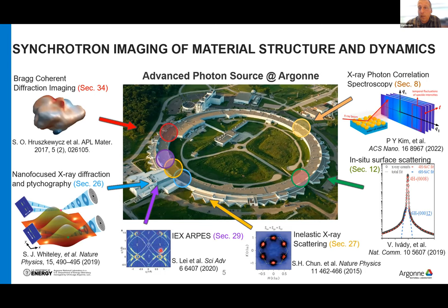But you can also tune the energy to look at excitations. So these fundamental electronic excitations, by using intermediate energy X-ray scattering, also fundamental dynamics of the system, the phonon dispersion, using inelastic scattering as well, and looking in situ, so into active growth environments, CVD growth, also etching, high temperature, and being able to probe structures beyond that. And as Dylan was speaking to, his beautiful results of X-ray photon correlation spectroscopy can also be looked at for this kind of self-assembled growth and morphology changes of these, either block copolymer driven or electrostatically driven, kind of bottoms up integration.